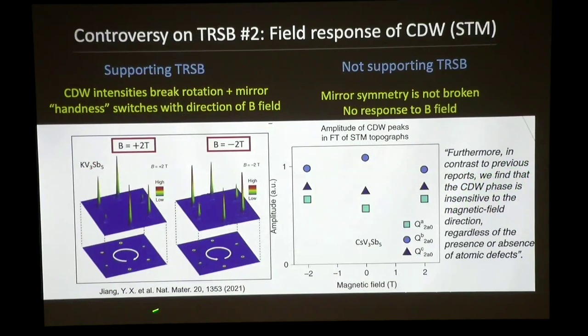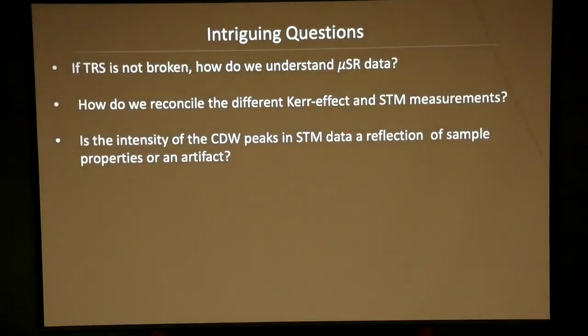Again, remember the STM data I showed you. In this sample, the charge density wave responds to magnetic fields. But then there was a later experiment that showed that there was no response of the CDW to magnetic field. So the question is, is time reversal symmetry broken? If not, how do we understand this muon spin resonance data? Can we reconcile these different measurements?